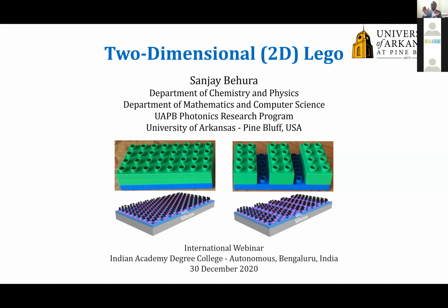And actually what happens when we place individual layers, for example, if we talk about only graphene and another graphene, it's called bilayer graphene. When we place one graphene on top of another, it's a bilayer graphene structure. And when they are not rotated, then they still possess their individual material properties. As soon as they are rotated at, let's say, just 1.1 degree, then the potentials undergo hybridization. So further hybridization happens between these two layers, and they now start acting as one material.